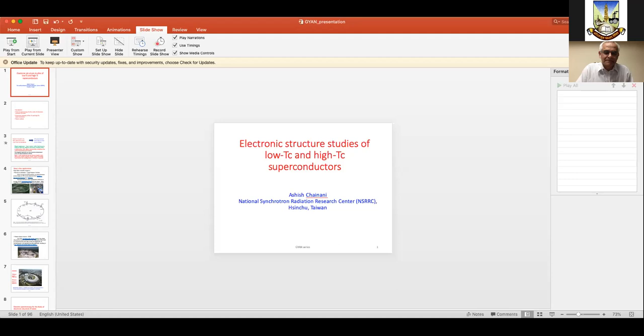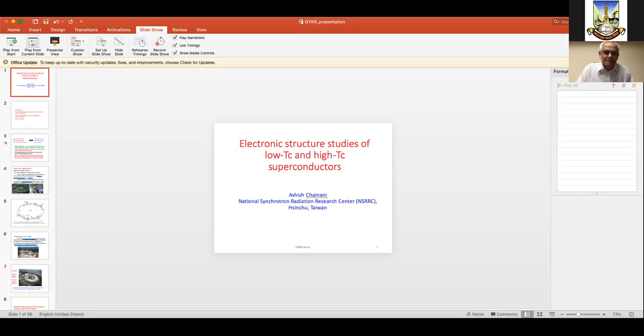Superconductors are special because they have no resistance — they can conduct electricity without power losses. One of the biggest applications of superconductors is the requirement of large volume, stable, and high intensity magnetic fields for magnetic resonance imaging. There's no alternative but to use superconductors, and all these applications use low temperature superconductors. It's a very big business dominated by a few companies like Oxford Instruments and Siemens, and most of them use niobium titanium superconductors, which have a TC of 10 Kelvin.